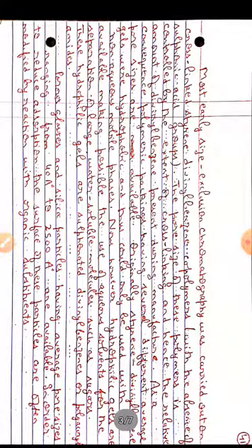Most early size exclusion chromatography was carried out on cross-linked divinyl benzene copolymers with the absence of sulfonic acid groups. The pore size of these polymers was controlled by the cross-linking, and hence the relative amount of divinyl benzene present during the manufacture.